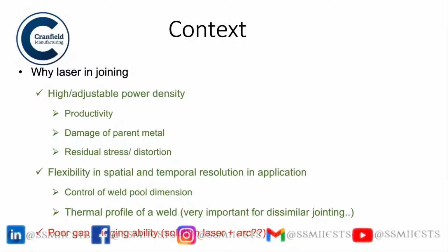What I'm going to talk about is, as I said as part of the context, why we use laser joining. The advantages are that it is highly adjustable, and you can obtain very high power density, which gives you higher productivity and less damage to the parent metal because the heat input is quite low, since you can weld very fast. That gives you the other benefit of lower distortion and thereby lower thermal stresses, residual stresses, and everything.